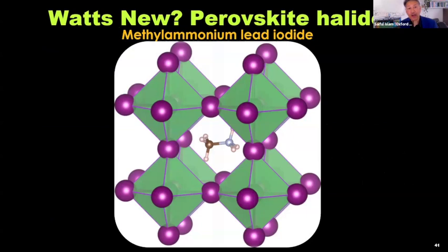So first of all, what is a perovskite? Perovskite has this beautiful 3D structure. It's, in this case, lead iodide octahedra corner sharing to form a 3D network. And at the A site, that central site, is methylammonium. The mineral perovskite is calcium titanate, but in this case, it's an organic-inorganic halide perovskite. There are other A cations like formamidinium and cesium, but this is the prototype material.